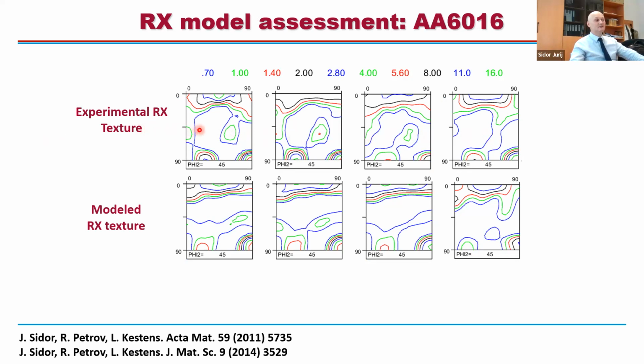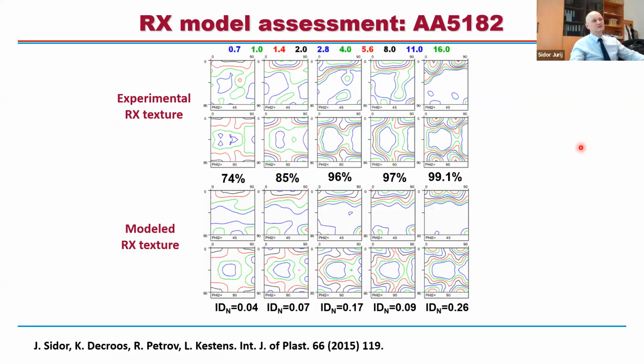In fact, we can nicely reproduce experimental textures. When we had different hot bands, we subjected this initial texture to different straining levels. We got different recrystallization textures. So here are experimentally observed recrystallization textures, and the ones which we could reproduce by our recrystallization model. So major components could be nicely reproduced. So it was done for 6016 alloy, and then also we did this for 5182 alloy.